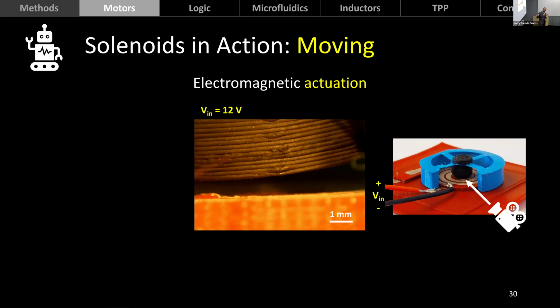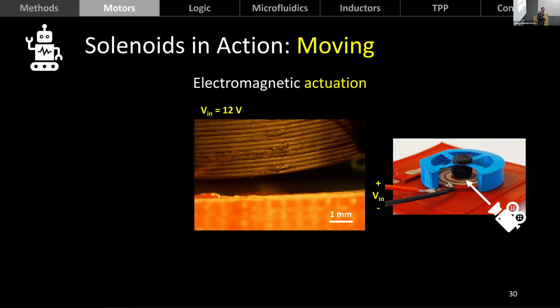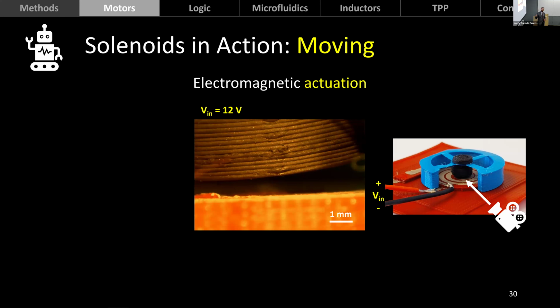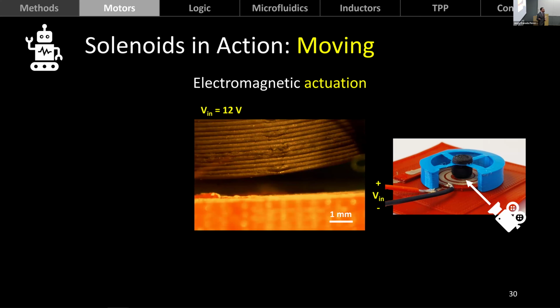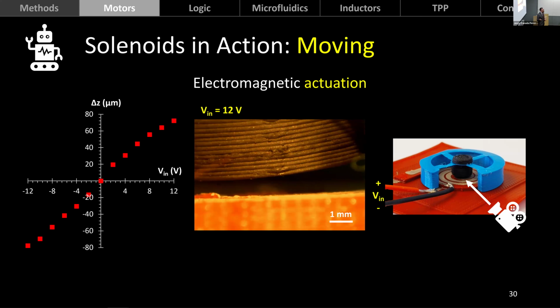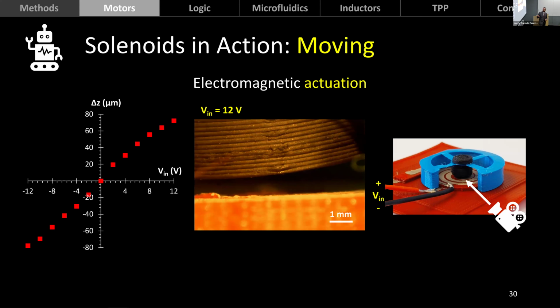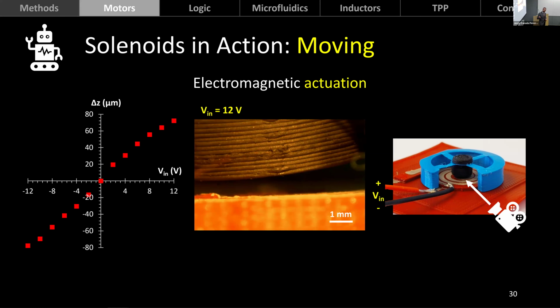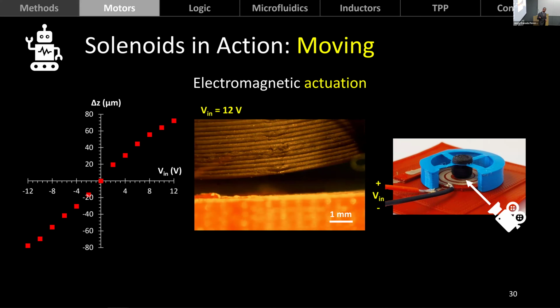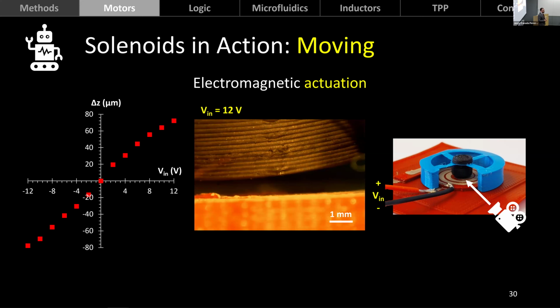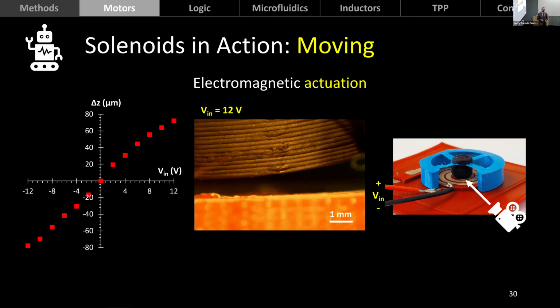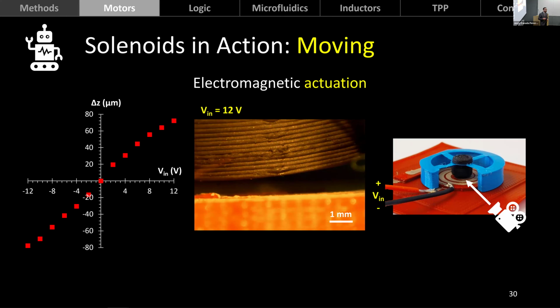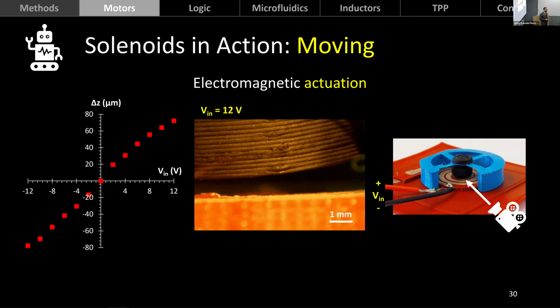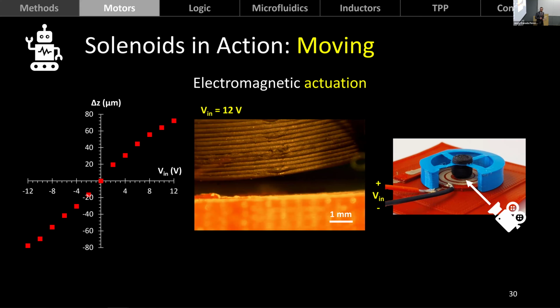And so by biasing this, by placing a voltage across the solenoid, we are able to generate attraction and repulsion forces on the magnets. And we characterize this by changing the bias voltage. And we were able to see that it's mostly linear, except at its edges where it seems like it's starting to saturate, which is something that we would expect from this type of device as the deformation becomes of the order of the width of the beams.